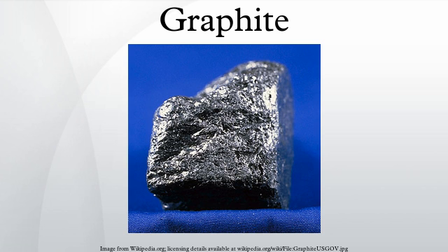Graphite and graphite powder are valued in industrial applications for their self-lubricating and dry lubricating properties. There is a common belief that graphite's lubricating properties are solely due to the loose interlamellar coupling between sheets in the structure. However, it has been shown that in a vacuum environment, graphite is a very poor lubricant. This observation led to the hypothesis that the lubrication is due to the presence of fluids between the layers, such as air and water, which are naturally adsorbed from the environment. This hypothesis has been refuted by studies showing that air and water are not adsorbed. Recent studies suggest that an effect called superlubricity can also account for graphite's lubricating properties.